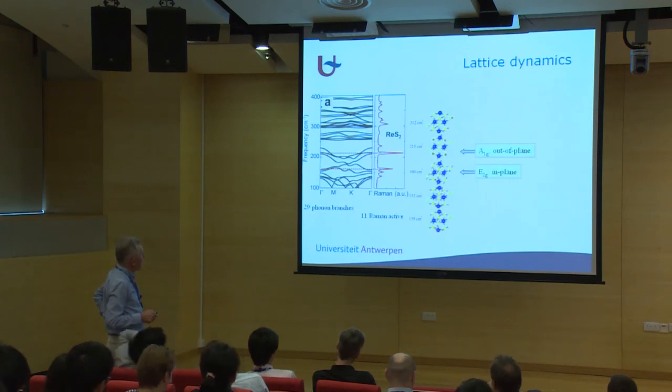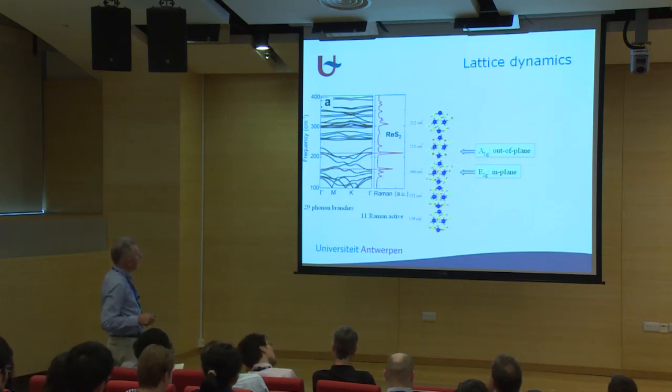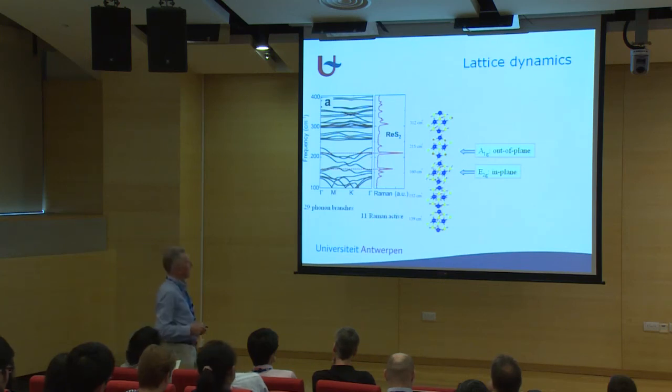And the dominant one is this one here. So that's the A1g out-of-plane motion, but you also see that you have a coupling in of in-plane motion, and the same with the E2g here. And these are some other modes here. Okay. So if you look at the eigenvectors, it's not all pure in-plane or out-of-plane.